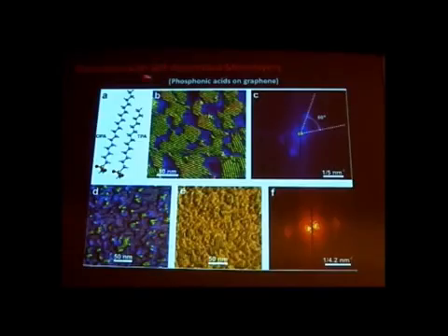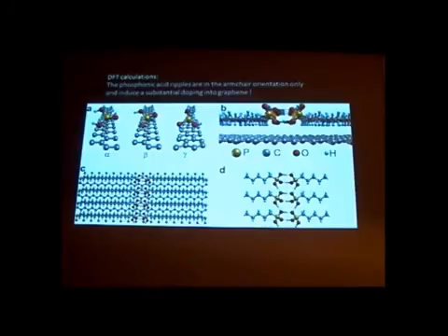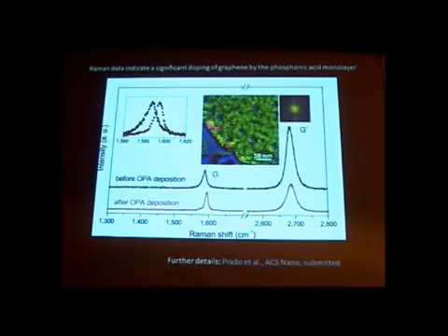And finally, I have recently made this decoration with self-assembled monolayers. So we prepare a solution of these organic molecules and put a droplet on the graphene. The graphene is in purple here, and we always see these monolayers formed as these ripples. If you do some calculations on these ripples, we see that the molecules are always oriented where the ripples are formed by the head groups of the molecules. So we have this in the armchair orientation only. And this induces a substantial doping of graphene, and this doping of graphene is actually measured by Raman scattering experiments.